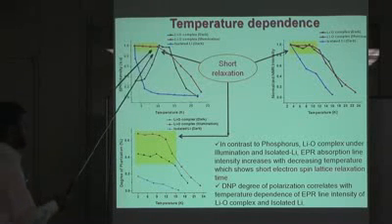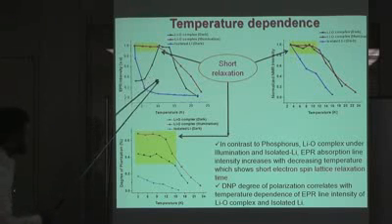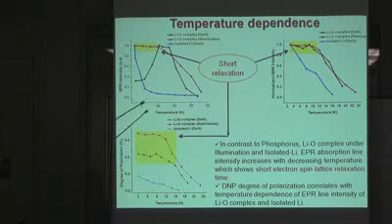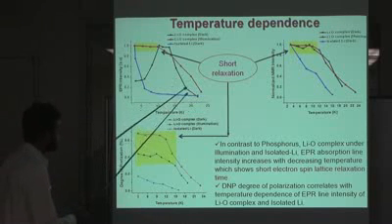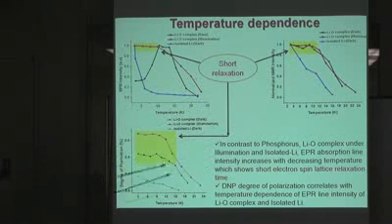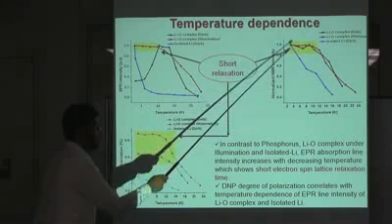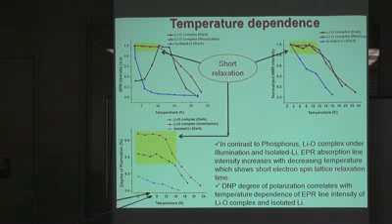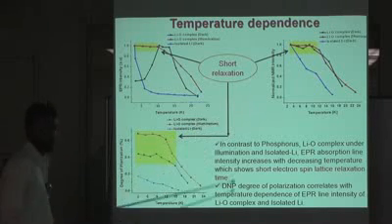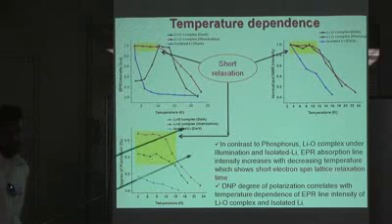We don't know yet exactly why the EPR line decreases, but when we observe the NMR intensity versus temperature, we record an almost constant NMR signal in the range of 3K to 10K, both under illumination and under dark condition.